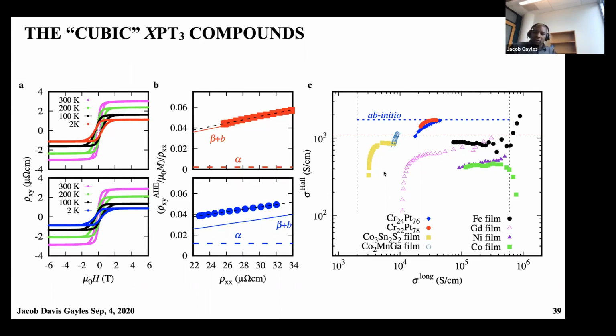Surprisingly, for this system, I didn't put it in the supplementary, but there's not a lot of anisotropy for different directions of the anomalous Hall effect. So from there, I would say the strain would not change it drastically either. It is very anisotropic in the magnetization. So for a cubic material, going from the 111 to the 100, which is also relevant in the theoretical calculations, I get something on the order of a milli eV. But the anomalous Hall transport is not very anisotropic. All right, thanks.